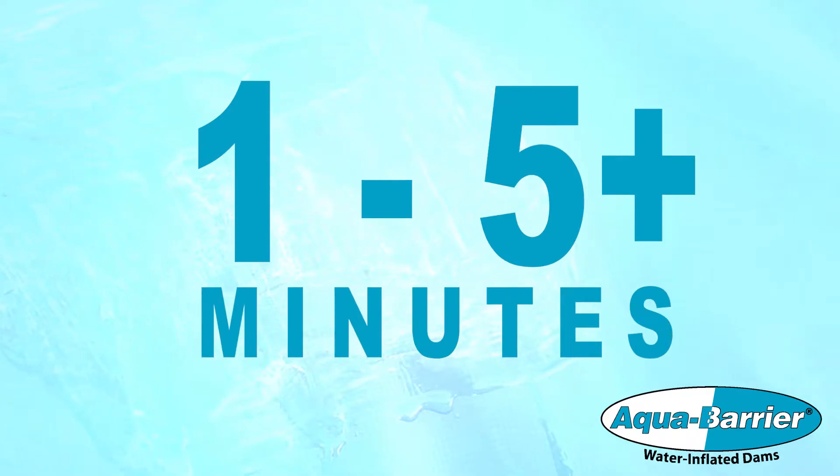Once applied, wait until the vinyl cement has changed from clear into a hazy white color. It will also become non-sticky to the touch. The time needed for this can span between a minute to more than five minutes, depending on weather and temperature variables.